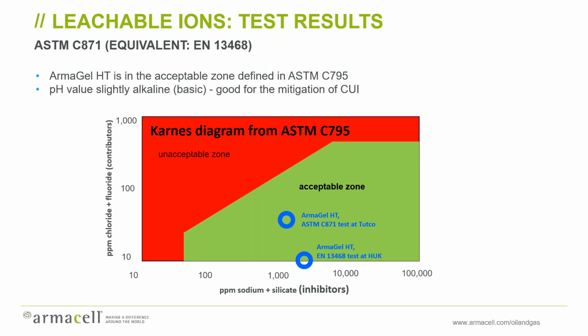And basically, if you're in the red zone, you're at risk of stress corrosion cracking. If you're in the green zone, then that risk is mitigated. And ArmaGel, those two blue circles there in two different tests, is well within the green zone. So that's great. Also, the pH value is slightly alkaline or basic. And again, that's good for mitigation of corrosion under insulation. You don't want an acidic product against your pipe.